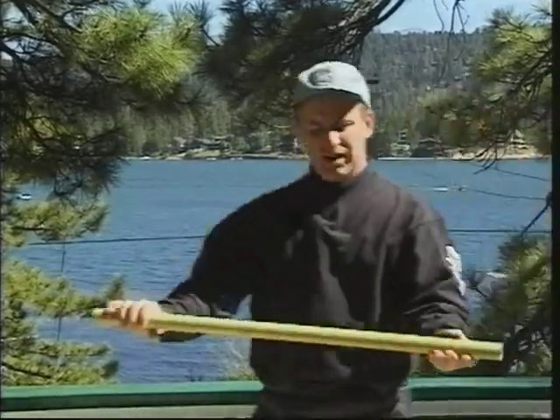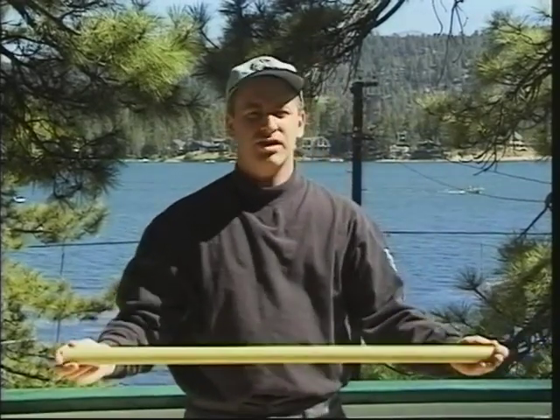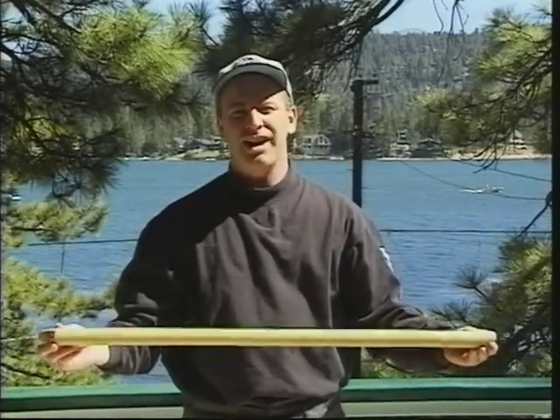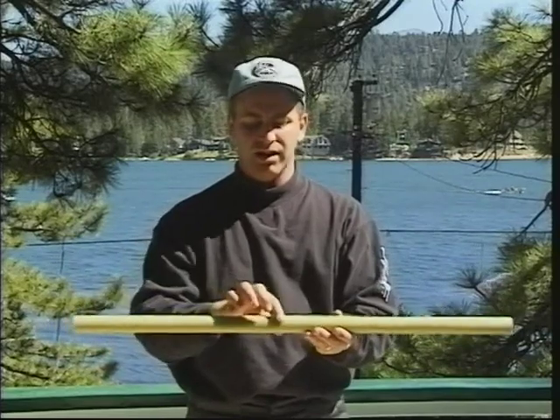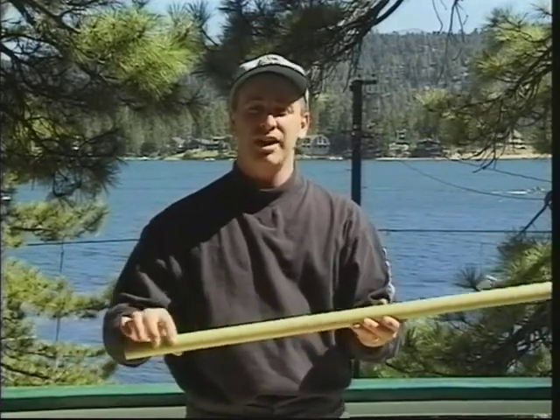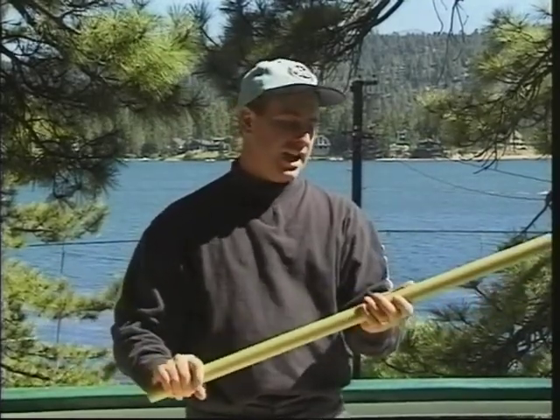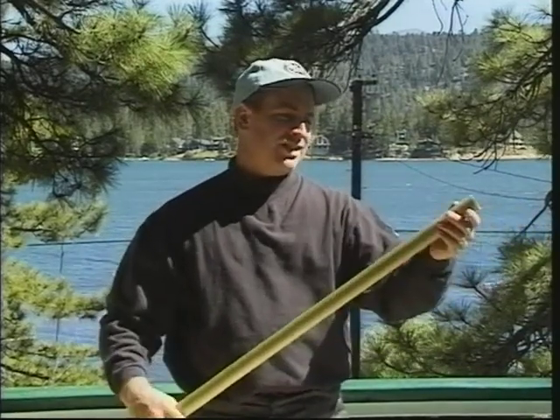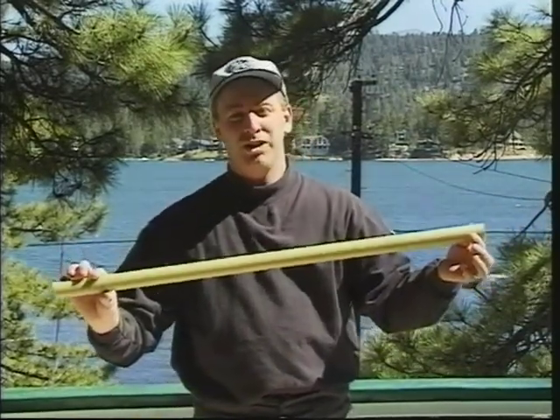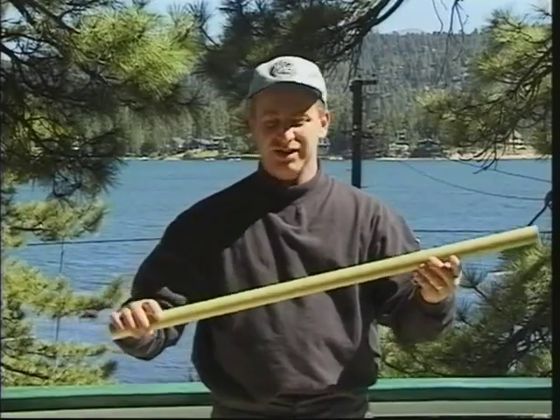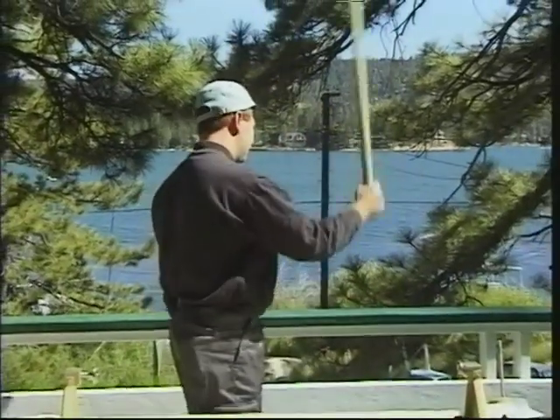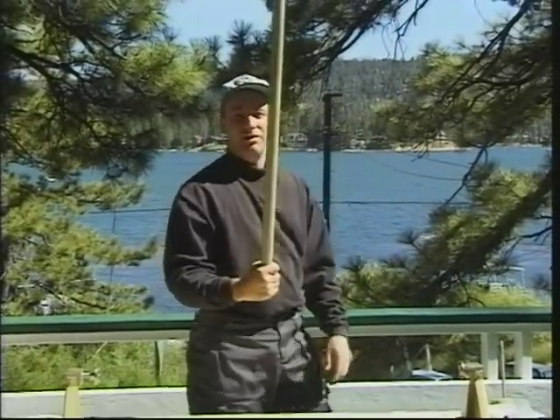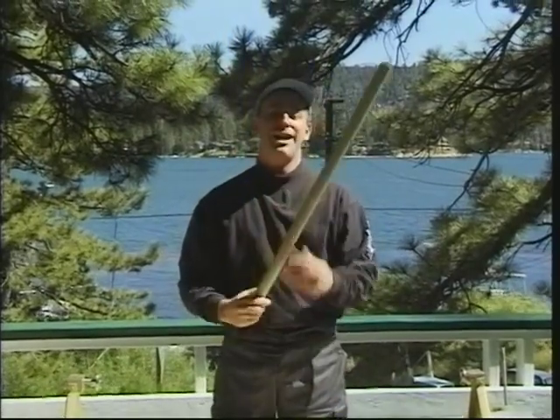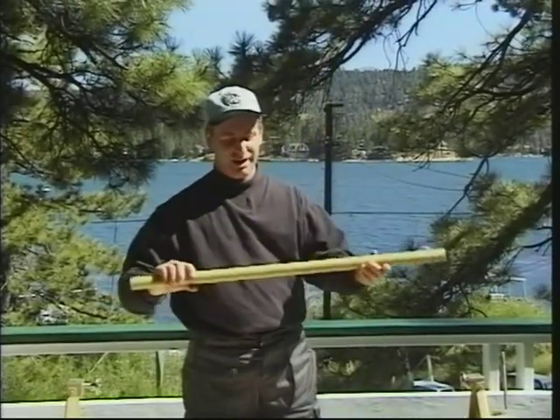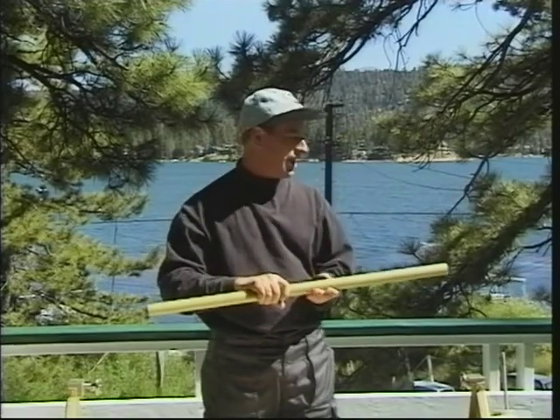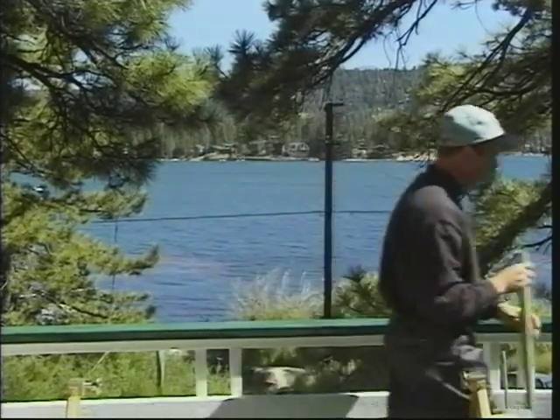Here's an example of just plain wrapping fiberglass onto a tube. I did this one on an 1¼ tube just to show that you can do it with smaller tubes. And this has 2 wraps around a paper tube, and I guess demonstrations prove more than anything, so a paper tube doesn't do that. So very, very strong again too. And that's just with standard glass.